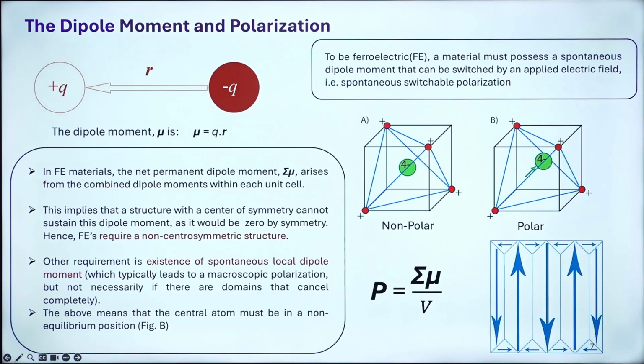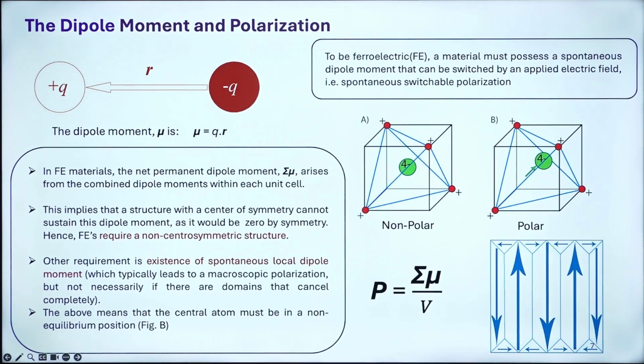As I told you, there is a connection between the dipole moment and polarization. To be ferroelectric, a material needs a dipole moment that can be switched by applying an electric field, and the net dipole moment arises from the combined dipole moments within the unit cell. The prerequisite is a non-centrosymmetric structure which lacks inversion symmetry. The other requirement is the existence of local dipole moments, which typically lead to a macroscopic polarization, but not necessarily if there are domains that cancel completely. These are the basic prerequisites for a material to have ferroelectric properties.